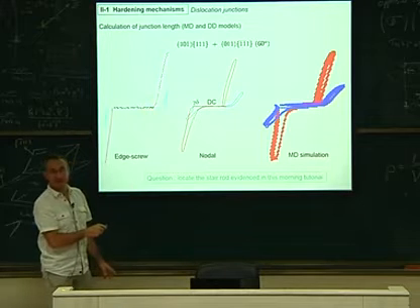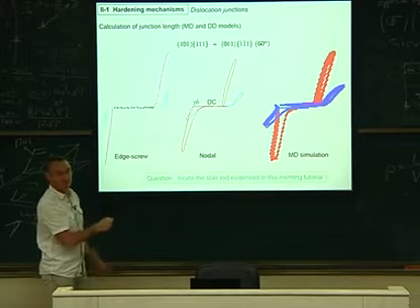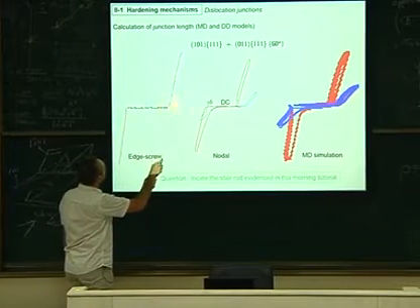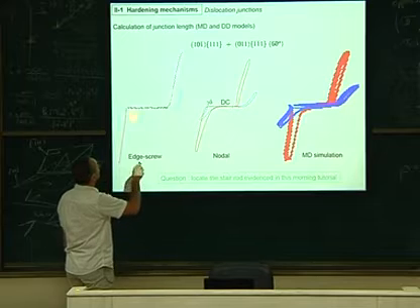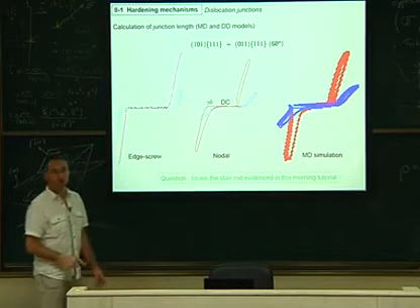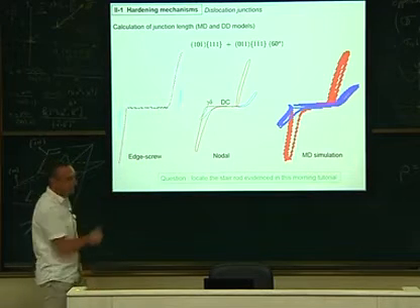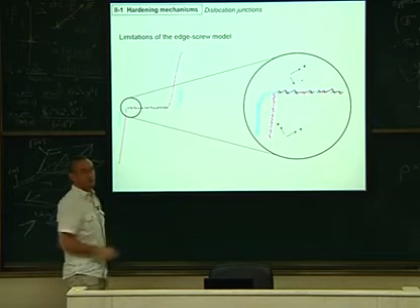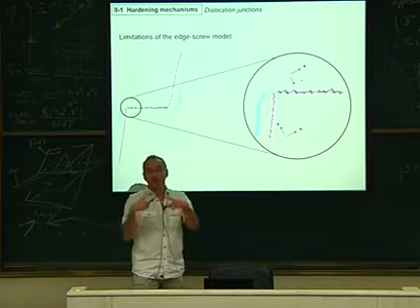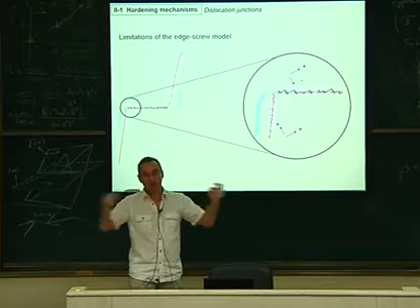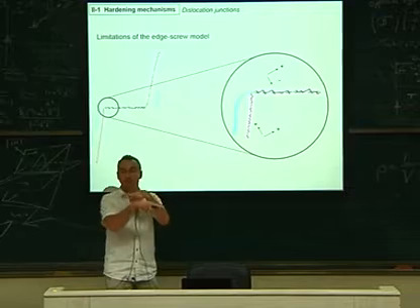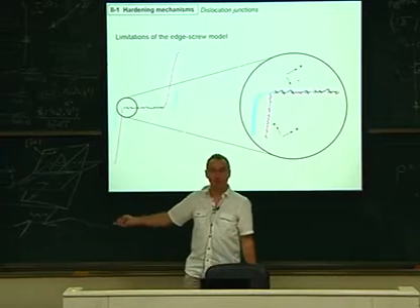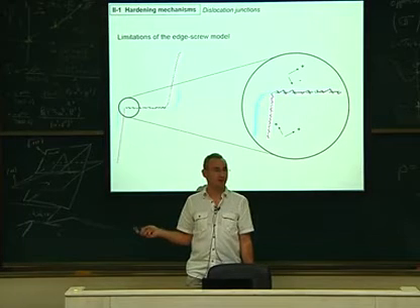And although my stupid edge screw model, my stupid DD code, the code I'm using every day, my old code, does the same. You can see that this is tangent, and this is acute, similar to there. Except that here there is something I call a sausage. It looks like a sausage, you see here. It's a sausage because if you zoom on it, it's just the superposition of two lines. In the edge screw model, there is no junction. We don't create triple nodes and merge and create junctions. We just superimpose lines, which is not good. It's not good because among the junctions I just showed you here, there is one that I will never be able to do with my DD code.